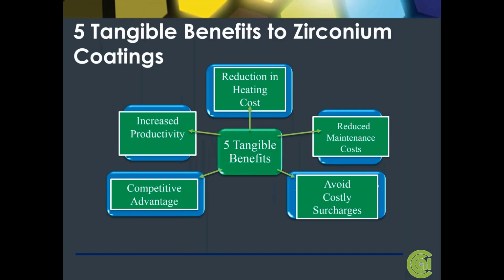And because there's less contact time required, you can increase your productivity. An iron phosphate process requires between 30 and 60 seconds to get a good crystal structure on the surface of the part for paint adhesion. A zirconium process takes between 15 and 30 seconds to get the same crystal formation on the surface of the part. So you can increase your productivity simply by switching to zirconium. You can feasibly double the capacity in the line.